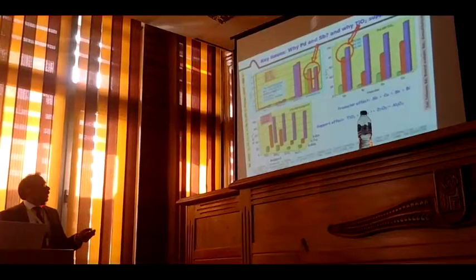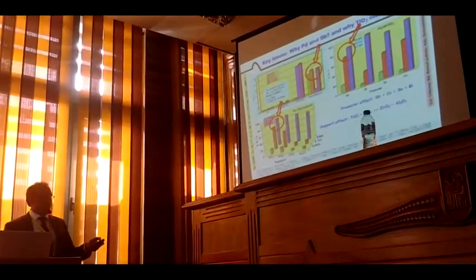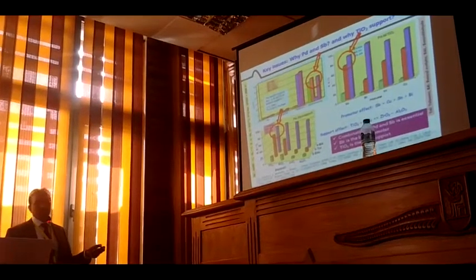So if you compare titania, silica, zirconia and alumina, you can see the highest conversion is achieved in case of titania, and high selectivity compared to all other supports. So what we learned from this study: combination of palladium antimony is essential. Antimony is the best promoter and titania is the best support. Now it's convincing that we need palladium, antimony and titanium,